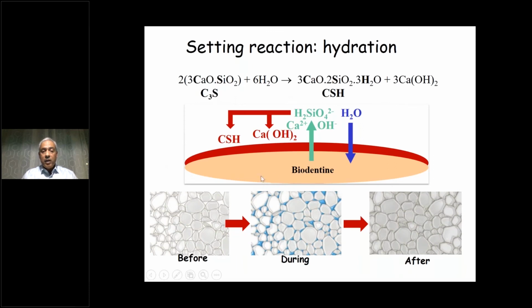So what happens when you mix the powder and the liquid is the following. You solubilize a part of the particles of tricalcium silicate with the liquid. That will produce what we call hydrogel. So the hydrogel will precipitate between and on the surface of the tricalcium silicate particles. And once setting is obtained, you reduce the porosity of the material. And when you reduce the porosity of the material, as you can see here, that means you will increase the mechanical properties. Also, the setting reaction produces hydroxyl ions and calcium hydroxide and some other components that we will discuss at a later stage. And these are very important for the function and for the regeneration of the tertiary dentin for the protection of the pulp.